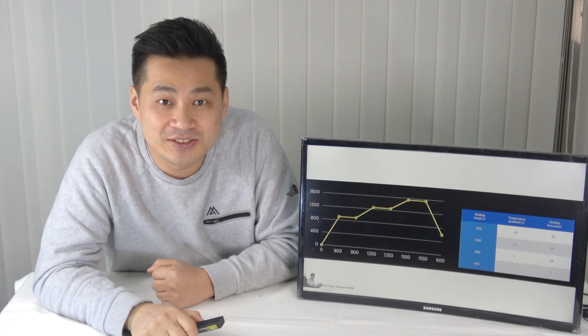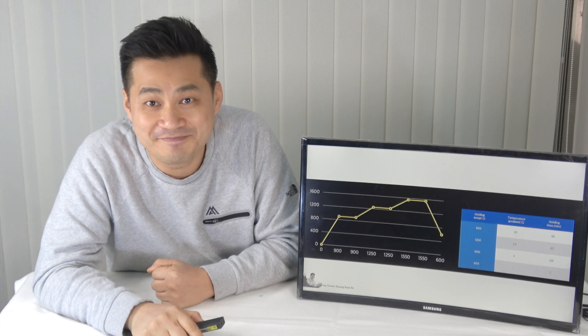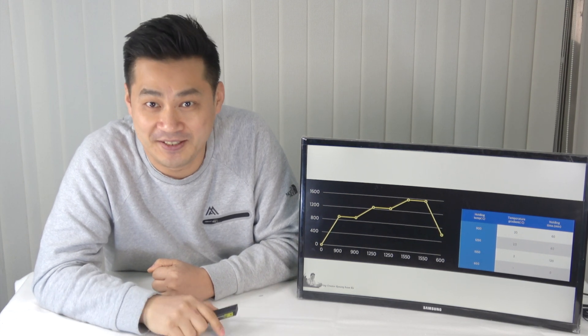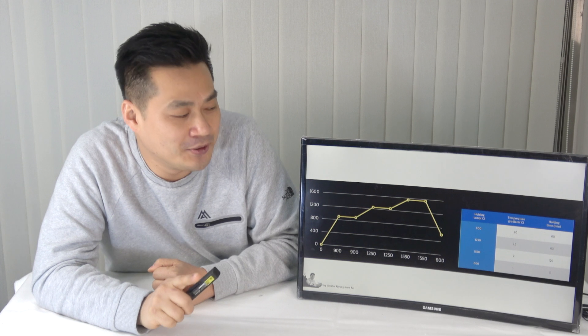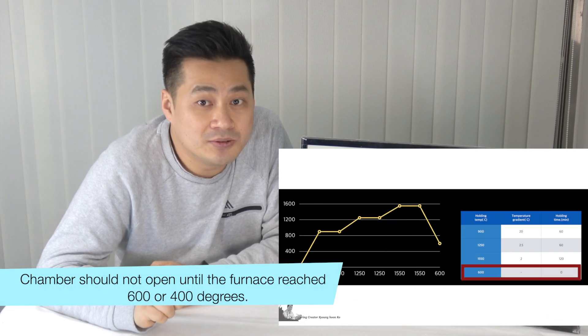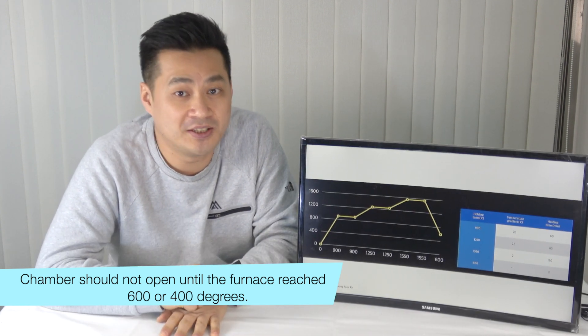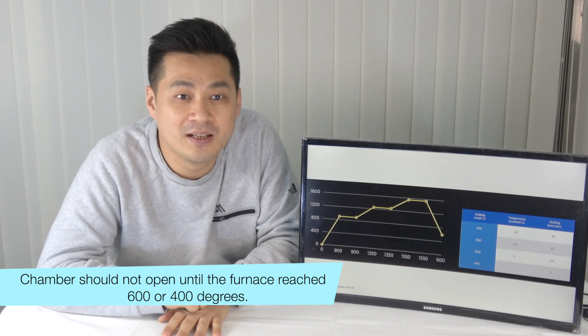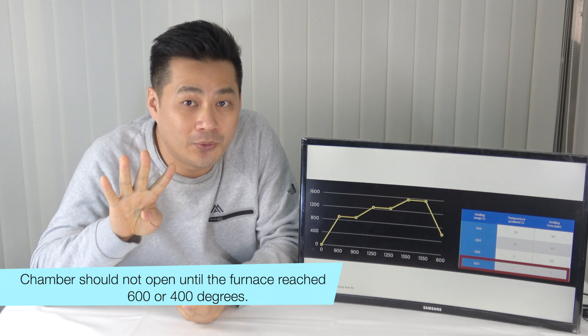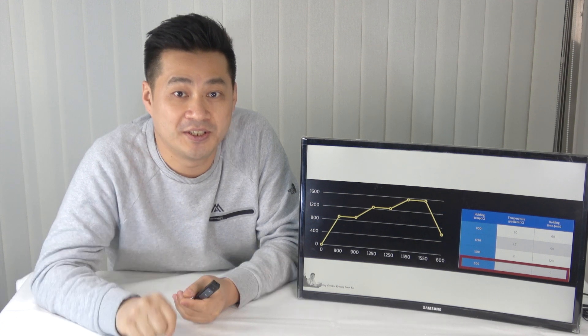For the cooling stage — cool slowly and slowly for stability. The most important rule of cooling is: do not open the chamber when the Zirconia is above 600 degrees. For big size and full-arch cases, wait until 400 degrees before opening.